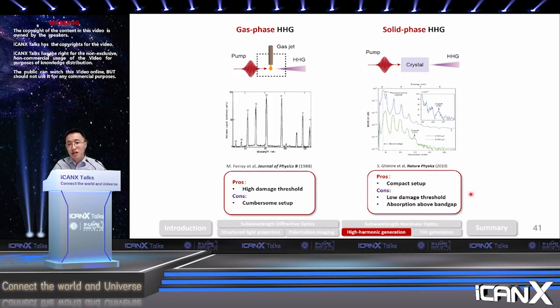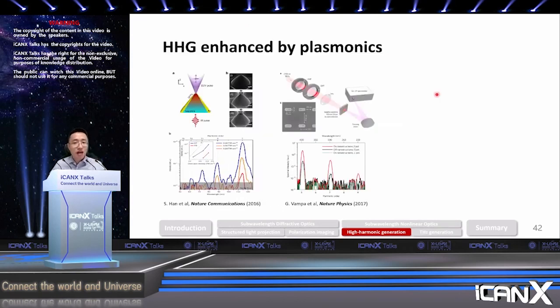One of them is that solid targets typically have quite a low damage threshold. And the second is that since we are oftentimes interested in high harmonic generation all the way to very high photon energy, in the extreme UV or X-ray range, all these nonlinear crystals may have quite large absorption because the photon energy is already above the material band gap.